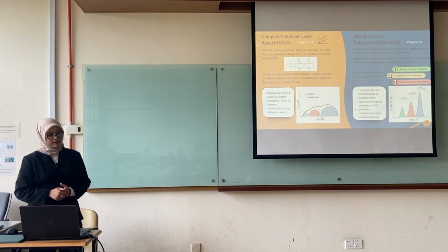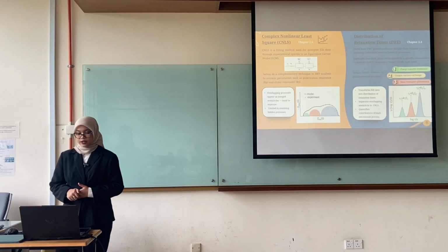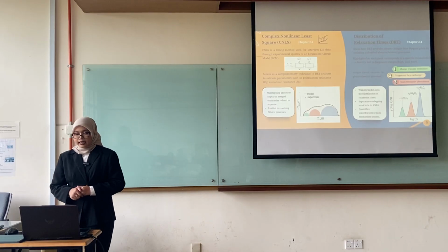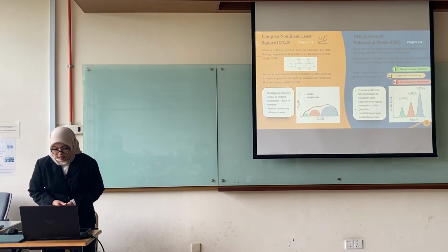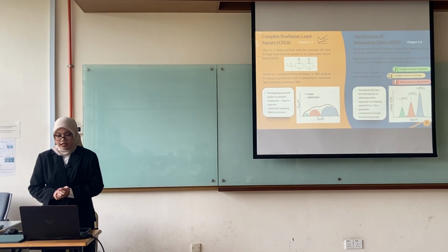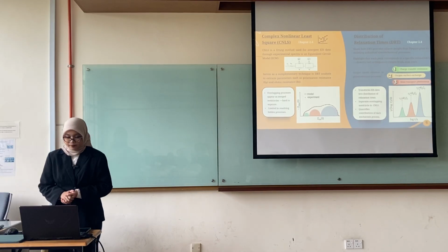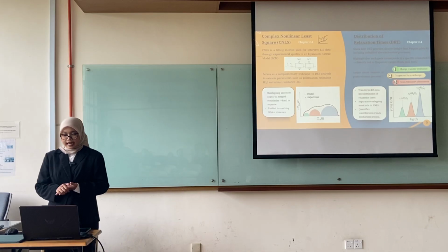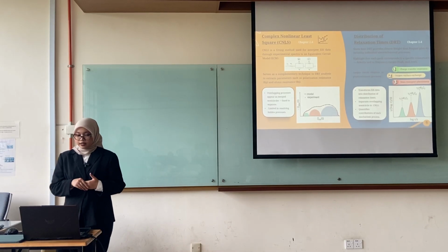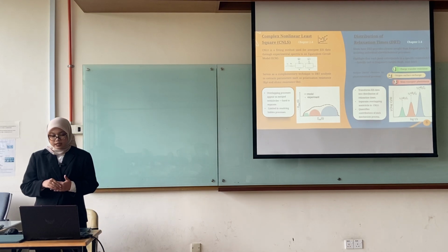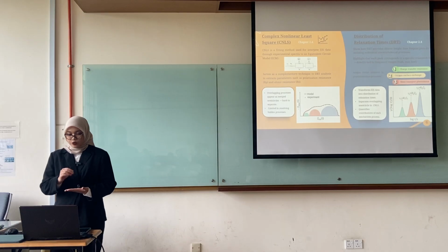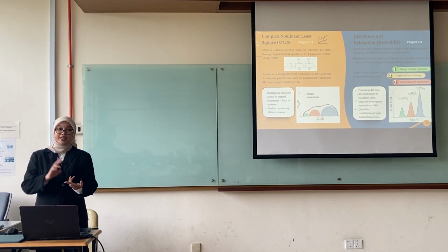Compared to that, the distribution of relaxation time (DRT) shows clearer insight than the Nyquist plot by resolving the individual electrochemical processes, where it highlights that each peak corresponds to a specific relaxation time, which is directly tied to the frequency range of high, medium, and low.